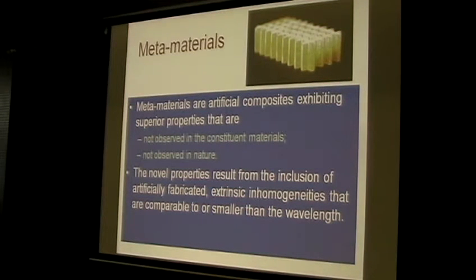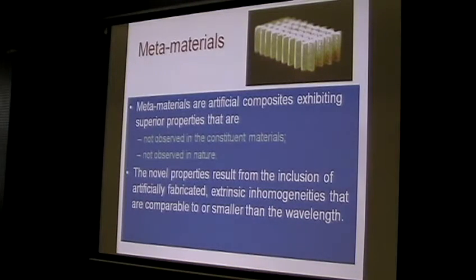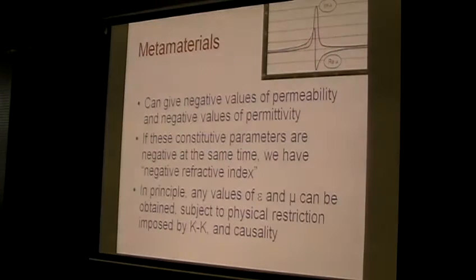Now, what distinguishes a metamaterial from a photonic crystal is not just the scale, because for a photonic crystal, the components can be very uninteresting by themselves. It is by the structure, by the way that they couple to light, by Bragg scattering, that gives you all these interesting band gap states and so on. But for the metamaterials, it is the other way around, the length scale of these is not so important. It is basically the structure of the individual element inside, the resonances that give you all the functionalities. Okay? And so the distinction is there.